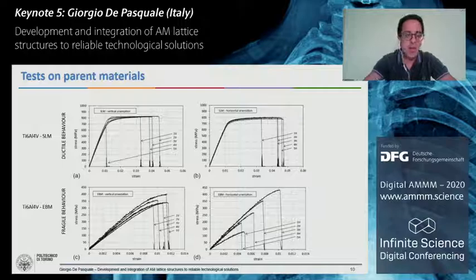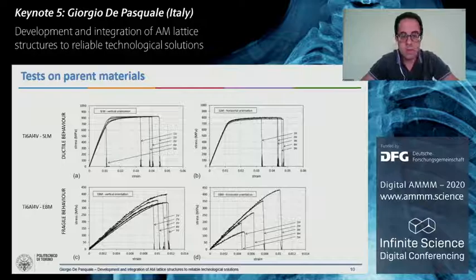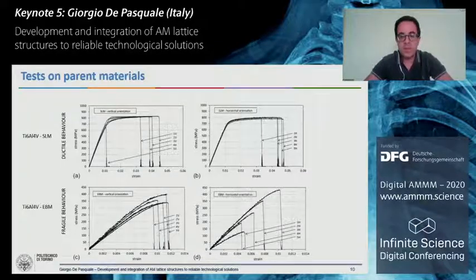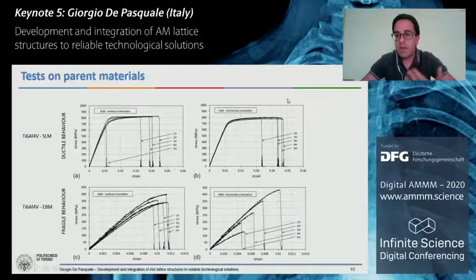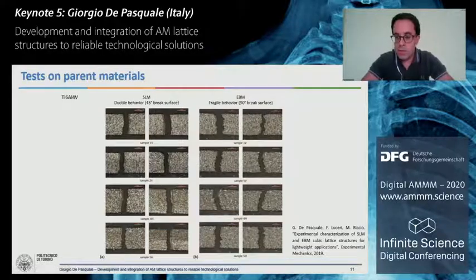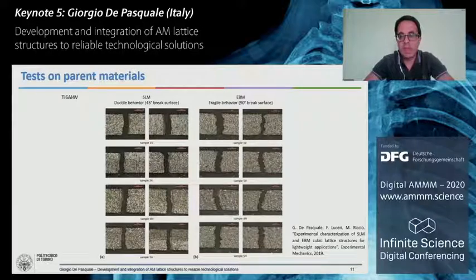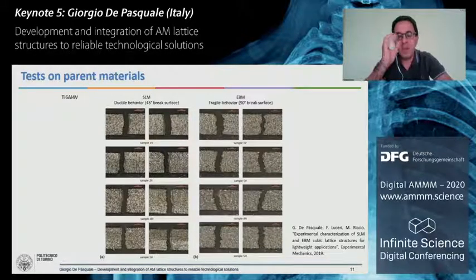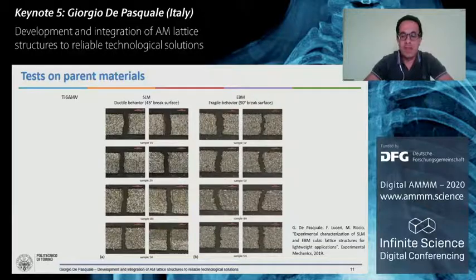In this case, we have a titanium alloy processed with the SLM process on the top line and with the EBM process in the lower line. We can see very different behavior, just to underline that the process is determinant in this case. The same thing is reported by the breaking surface of the samples. We have a 45-degree breaking surface orientation, typical of ductile materials, in the first case on the left, and a 90-degree orientation, typical of fragile materials, on the right.